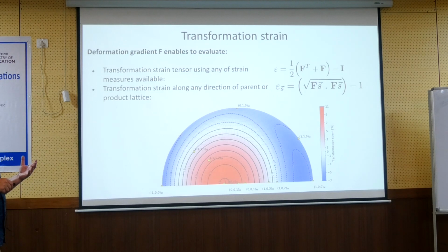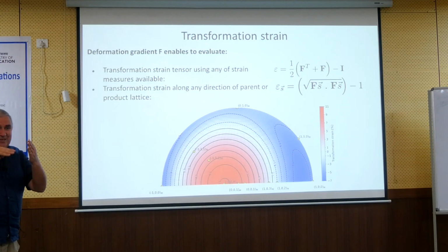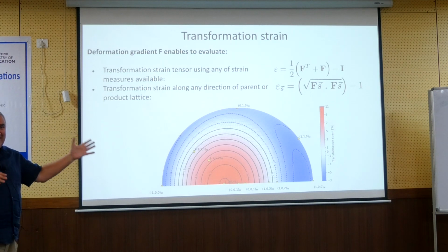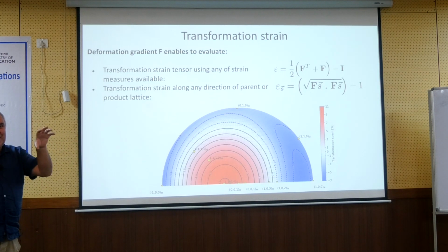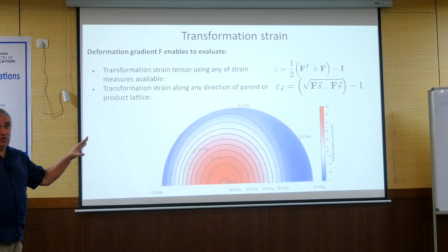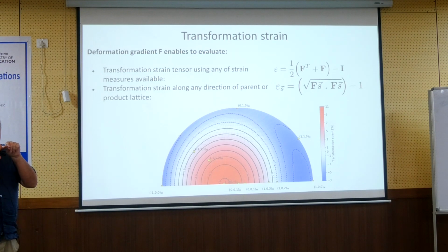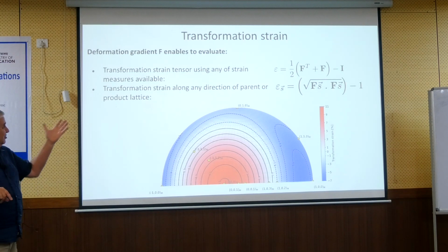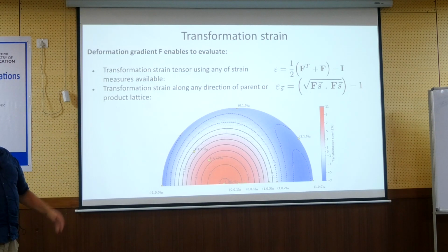Because why? Because people have this laminate on the other side, but we don't have any laminate. I am now talking about change from austenite to single variant of martensite. You remember most of the experiments which I shown so far kind of suggest that the martensite lattice is oriented in one particular way, even in polycrystalline state. And so that's why we plot it in the austenite in martensite coordinates. So this is the equation for calculating it in martensite coordinates.